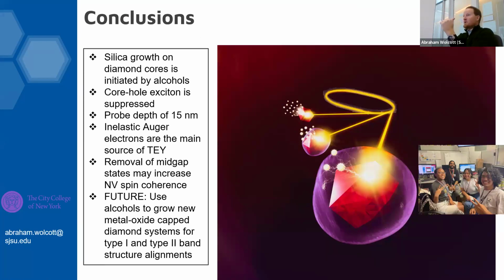The silica growth on diamond cores is initiated by alcohols, not by the carboxylic acids, which are originally on the surface. The core hole exciton can be suppressed. The probe depth can be found to be about 15 nanometers, and inelastic Auger electrons are the main source of our total electron yield. Importantly, we're removing mid-gap states that may increase NV spin coherence times, which I think Peter Maurer and his group has confirmed, which is nice because I wrote a proposal which was rejected and they said it wouldn't work. And Peter Maurer's group has shown that it has worked. So that reviewer was wrong.